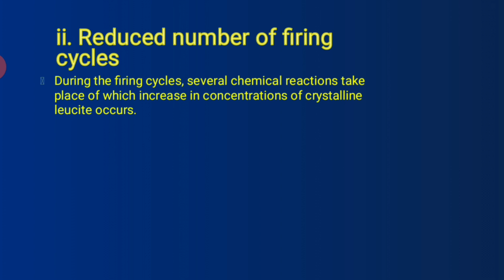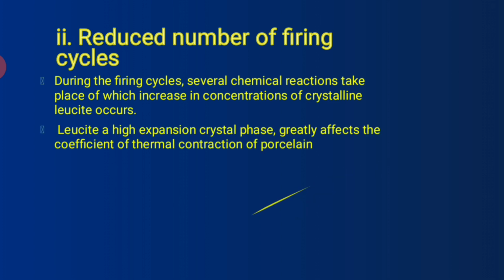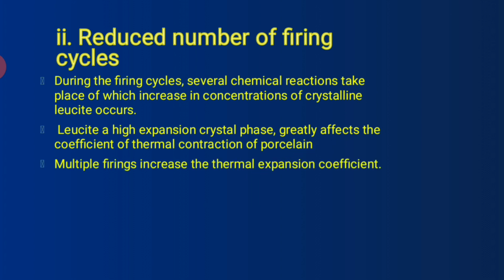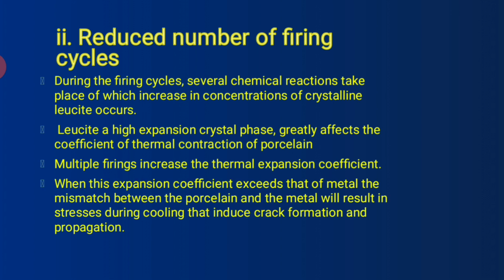Now second is reduced number of firing cycles. During the firing cycles, several chemical reactions take place, of which an increase in concentration of crystalline leucite occurs. Leucite, a high expansion crystal phase, greatly affects the coefficient of thermal contraction of porcelain. Multiple firings increase the thermal expansion coefficient. So when this expansion coefficient exceeds that of metal, the mismatch between the porcelain and the metal will result in stresses during cooling that induce crack formation and propagation.